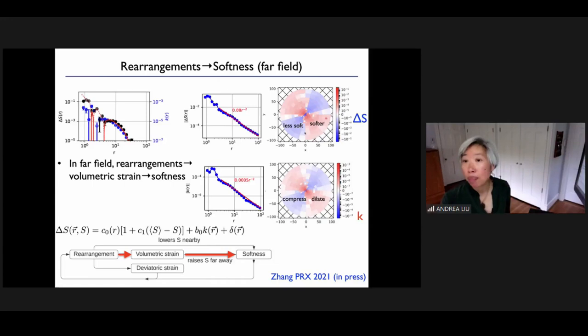You see it has the same dipolar form as the volumetric strain, and in fact the same decay with distance. And if I just look at the angle average, it looks like the transient piece of the volumetric strain, okay? So in the far field, that's the red curve. Sorry, softness is black. Oh, hold on. The blue is the volumetric strain, okay, and softness is black, and it agrees well. All right, so what that tells us is that in the far field, rearrangements give rise to a volumetric strain, and that is what is enhancing softness far away.